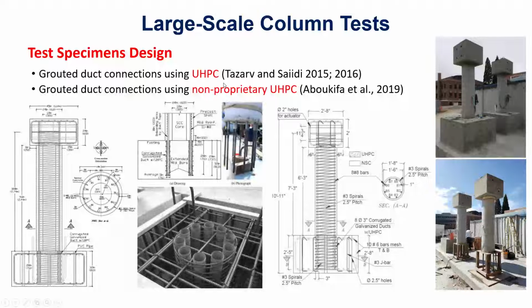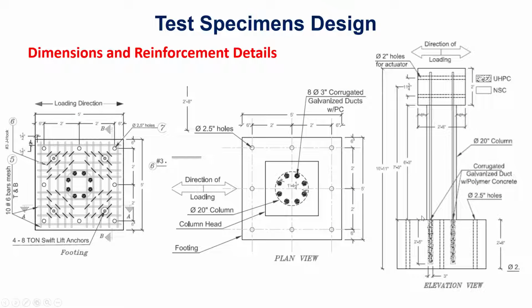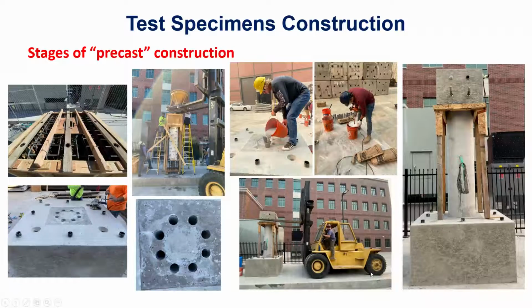We used some of the previous work that was done here at UNR that used UHPC, some of the work that was done by Tazarv and Saiidi, and some of the work that we did for Caltrans a few years ago using non-proprietary UHPC. So same research team, we did this for Caltrans. So we used some of these columns so that we can compare, as you'll see later in the last slide, the reinforcement details and the dimensions of the specimen, as you can see here, and the construction.